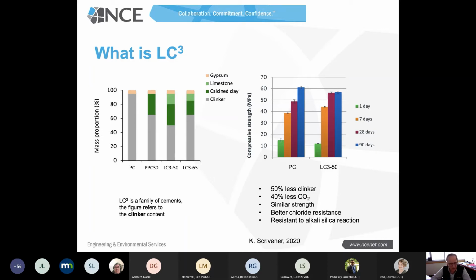But we're getting rid of the major component by reducing that clinker, and then we're going to replace it with limestone, calcined clay, and then gypsum. So gypsum, of course, is part of Portland cement. It's always been there. Limestone, again, there's a synergy that's been shown between ground limestone and SCMs like fly ash. And in this mixture, the SCM that's being used is calcined clay. So that is probably the biggest difference between what we would consider a conventional concrete mix and this technology, is the calcined clay.